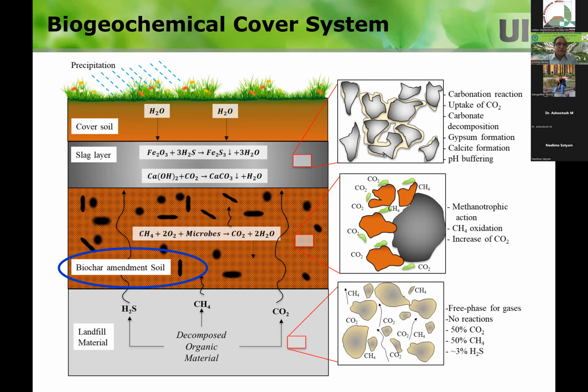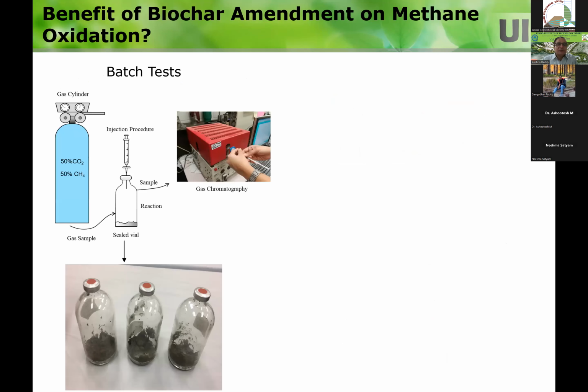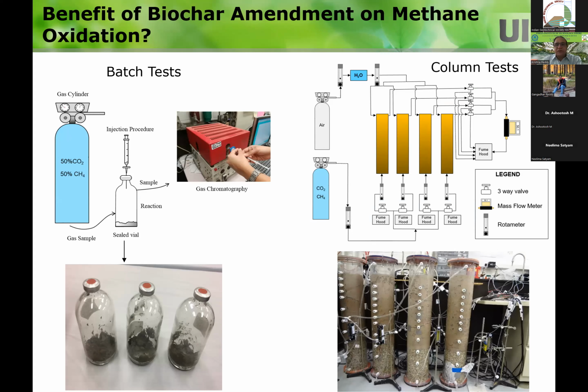Now, let's look at this a little bit more. We said, let's understand how they work. For this biochar amended soil, we did more investigation. We did many batch tests, and we also did column experiments. For batch experiments, you take small glass bottles, put the material in, put the gas in, seal it off, and then collect gas samples to see what is happening to the gases. If methane is converting into CO2, that is reflected in the concentrations when you take a sample and measure how much methane and CO2 there is.